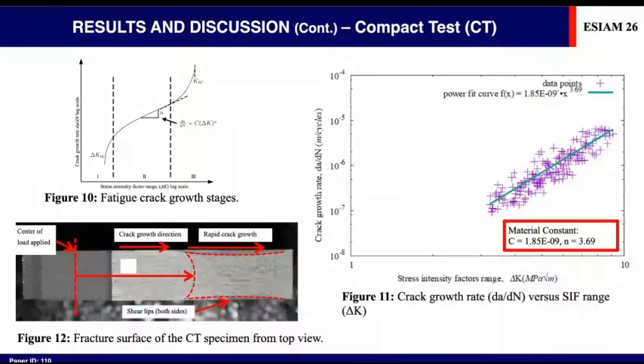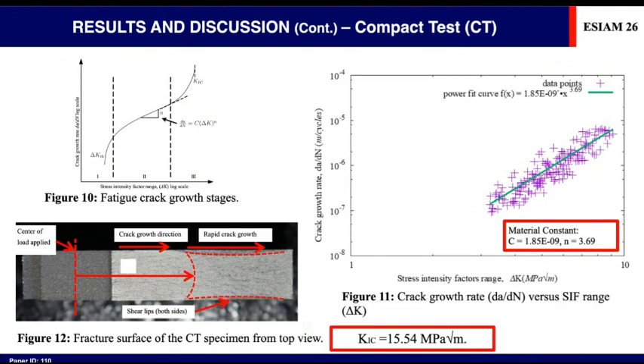Figure 12 presents the fractographic assessment of the CT specimen. During pre-cracking under constant loading, the crack propagation is stable and linear, producing a relatively smooth fracture surface. However, once the crack reaches approximately half of the specimen width, rapid unstable growth occurs. The fracture surface becomes rougher, and small shear lips are observed along the free surface, indicating predominantly brittle behavior with limited plastic deformation. Monitoring the shear lip formation is essential to ensure experimental validity. Therefore, using the measured critical crack length prior to instability, the critical stress intensity factor was calculated, giving a KIC value of 15.54 megapascal square root meter.